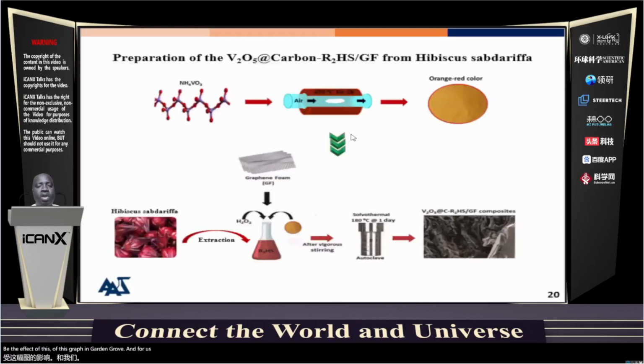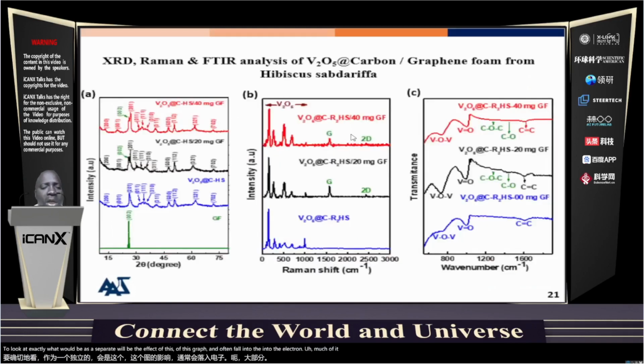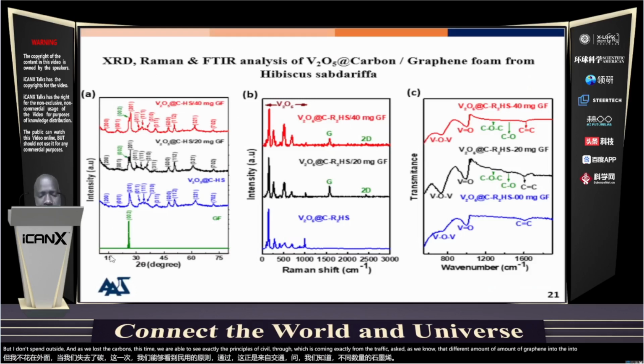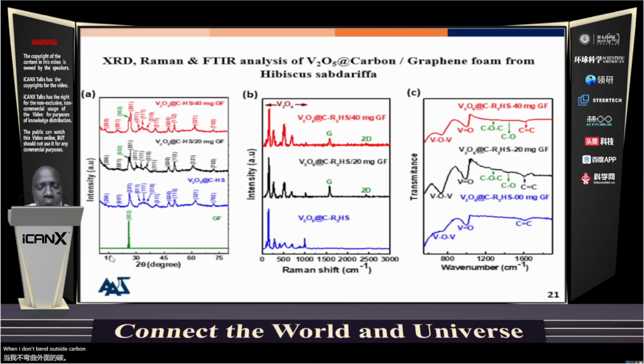So we have used the same process for the synthesis of vanadium pentoxide, carbon, and graphene foam, to look at what will be the effect of this graphene foam in the electrode material. Looking first at the characterization to see what we have produced, the X-ray diffraction in figure A shows the orthorhombic vanadium pentoxide as well as the carbon. This time we are able to see the presence of the 002 peak, which is coming from the graphene, as we loaded different amounts of graphene into the vanadium pentoxide carbon composite.